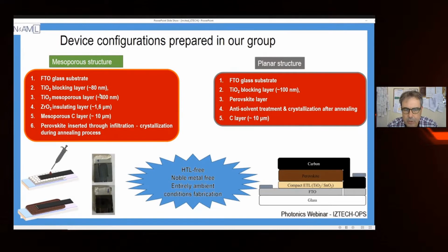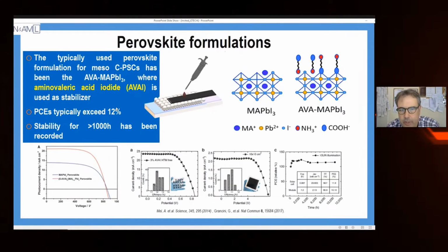Regarding the previous structure, the mesoporous structure, usually if you put a perovskite like methylammonium lead iodide, this one here, we have some problems with the interlayers between carbon, oxide, and the perovskite. This comes from the fact that oxides and carbon have different behavior. In the case of oxides, it is a hydrophilic environment for the perovskite. On the other hand, the carbon is not hydrophilic, so we have the problem of how we can put the perovskite into the pores there. That's why in that specific technology, we use an additive, which is an acid, aminovaleric acid iodide.